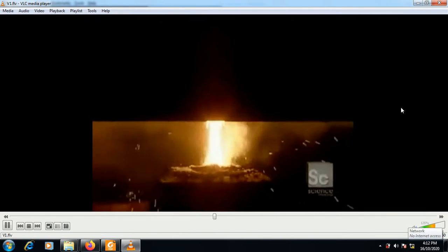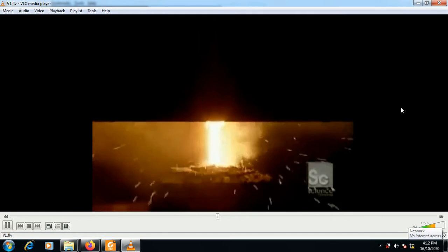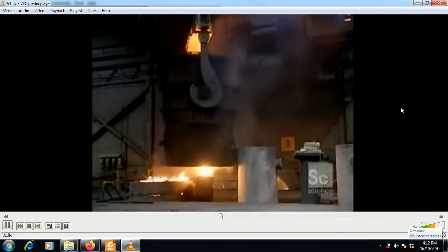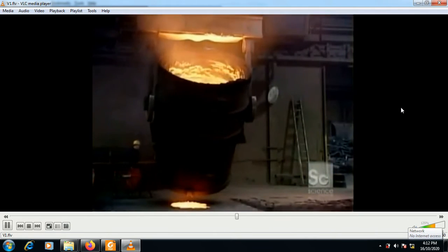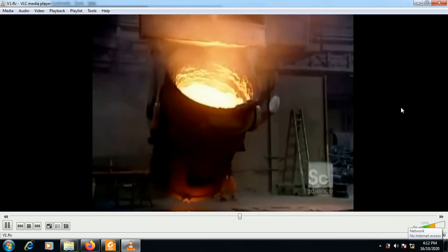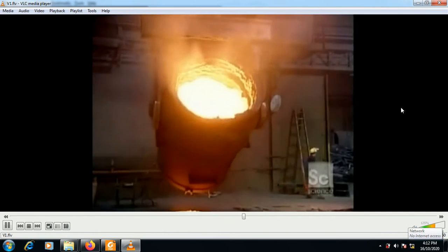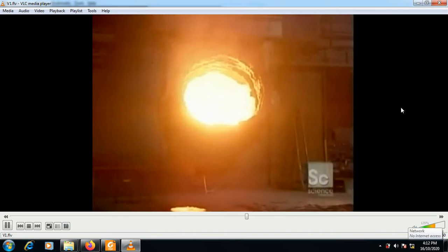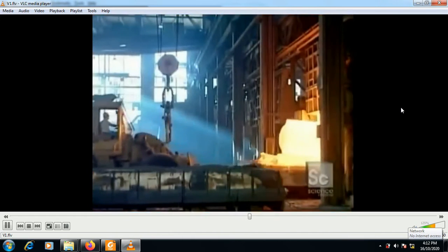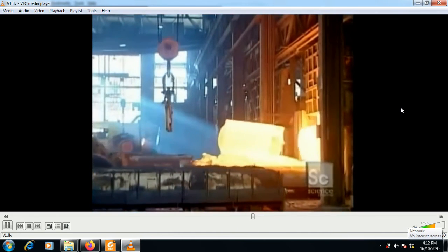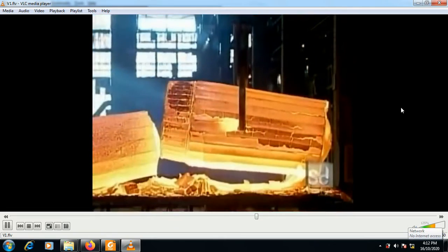Now they cast an ingot, a block of steel that they'll shape into a forging. The molten metal flows out the bottom of the ladle into a mold below. This bottom pouring, as it's called, makes for a smoother casting because liquid flowing downward doesn't swirl around as much as liquid poured sideways. This forge can cast ingots weighing up to 46 tons. After several hours, the ingot solidifies, and they turn the mold upside down to extract it.